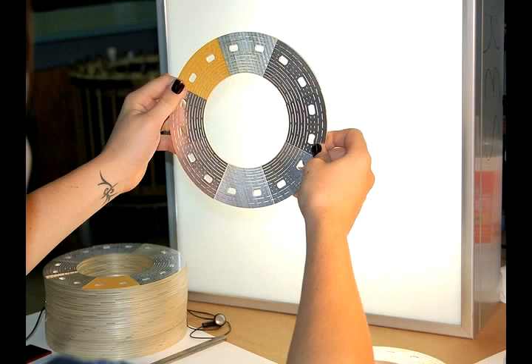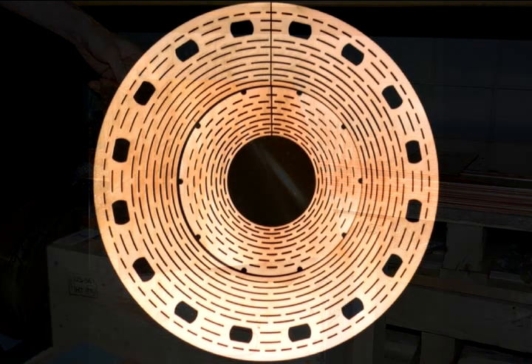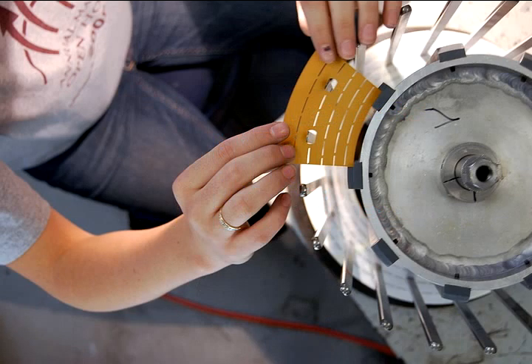And so to make these hold themselves together, we have to use very high strength copper alloys. So these disks, the highest field ones, are made from an alloy of copper and silver that's actually stronger than the steel that you see in the beams behind me. Yet it has electrical conductivity, 75% that of pure copper. So by combining this very high strength material, making these rings of conductor, providing a cooling system, we're able to get to much higher fields than you could with a simple wire wound coil.